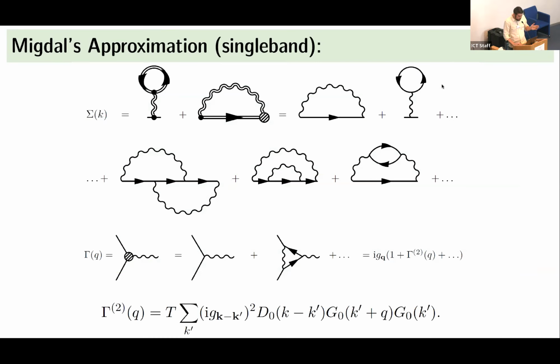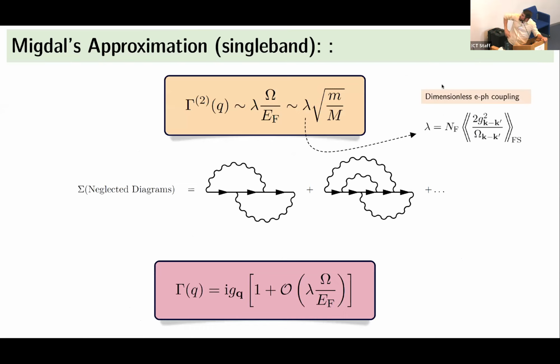So just a quick refresher, what is Migdal's approximation? It basically says that in the electron self-energy with a simple electron-phonon interaction, the main term that we might keep to describe the electron-phonon vertex is just this first-order diagram. The next higher-order diagram is usually neglected, and that kind of gets rid of all the crossing diagrams that look like this. And Migdal's argument was basically that you have a nice adiabatic system where the lattice moves a lot slower than the electrons, and this combination of the adiabatic ratio and the electron-phonon coupling should be small for this approximation to work.